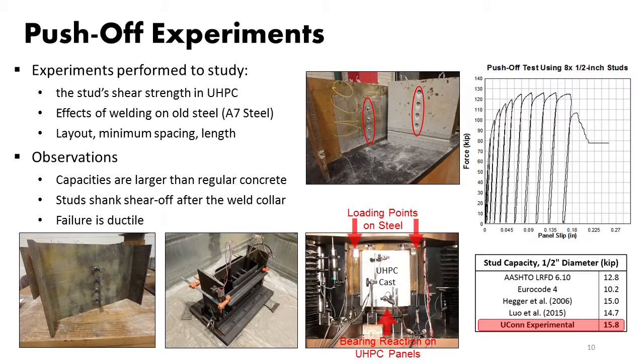And here you can see a column of four studs. This is the specimen before concrete is cast. This is the form. And here you can see the specimen in the load frame. So we apply the load from the top on the steel beam, and the concrete cast is sitting on a spherical bearing. So it shears off those studs. And this is the way they fail, as opposed to studs in traditional reinforced concrete, where it's a combination of bending of the stud and crushing of concrete. In ultra-high-performance concrete, essentially they shear off, and they give us a very large capacity and also surprisingly large ductility. So far we haven't had any issue with the weld breaking off.